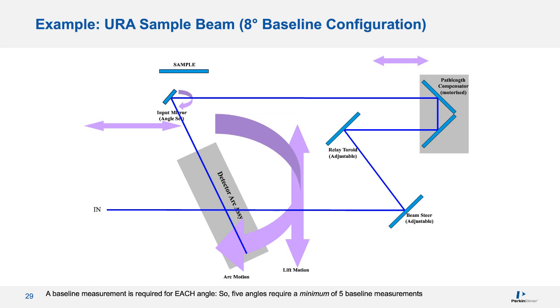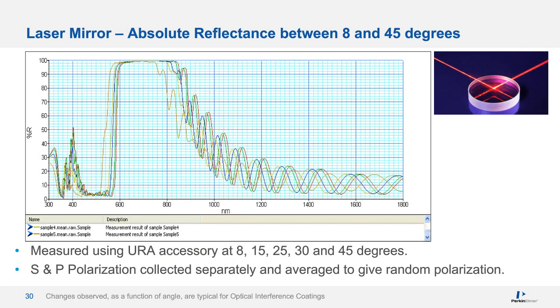Here's an example of some specular reflectance data for a laser mirror. A laser mirror is broadly defined as a mirror with a reflectance across some wavelength range of at least 99%, so it can certainly be higher than that. This particular laser mirror was measured at 5 different angles, from 300 to 1800 nanometers. In this case, both S and P polarized measurements were made, such that the average depolarized values were calculated and shown here. The shift to lower wavelengths as a function of incident angle is very typical for the interference type coatings typically used for laser mirrors. Note that one baseline is required for one particular angle, so 5 different angles of incidence would require 5 different baseline measurements prior to measuring the sample of interest at those angles. This does add to the startup time.